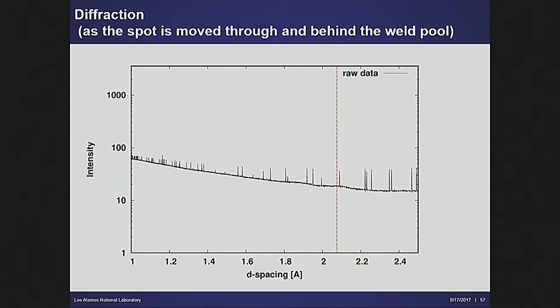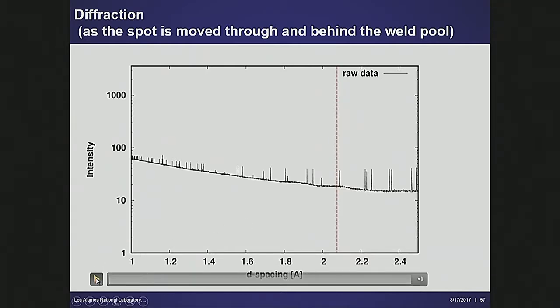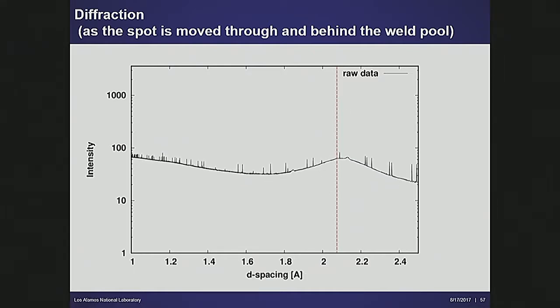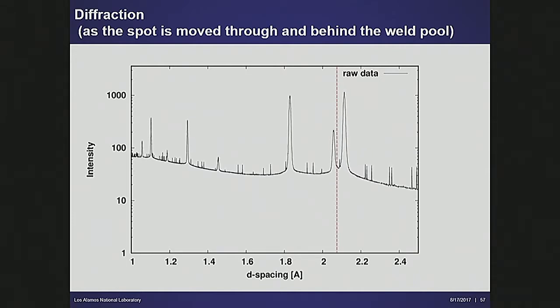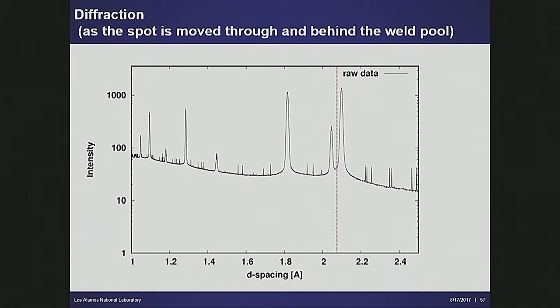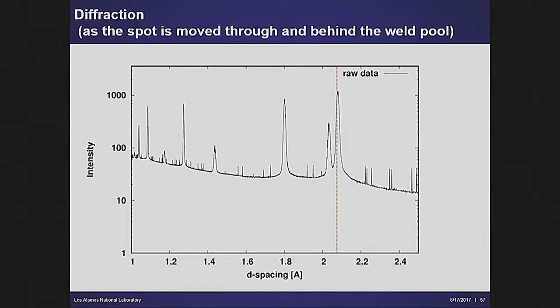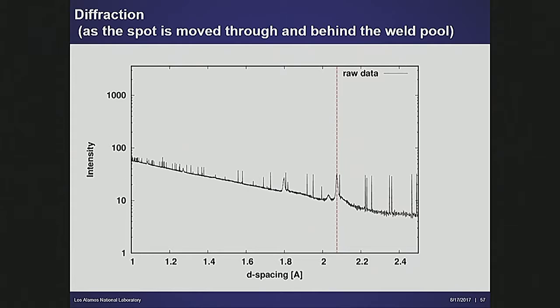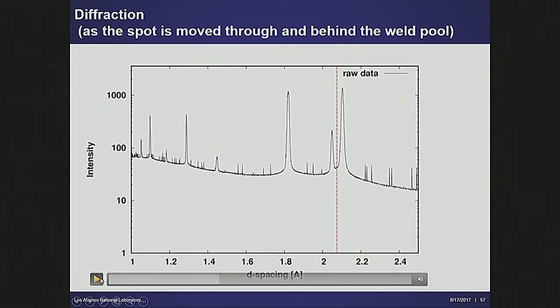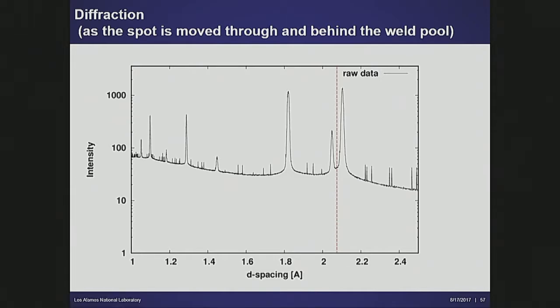If I integrate those rings to give you diffraction patterns that you're more familiar with, again, ignore the spikes. This is just the diffraction images of the integrated rings as you track it backwards and forwards. You can see the diffraction pattern changing. A couple of things to note. I'll run it again. Look for the bump here, which is molten. You can ignore that jump right at the end. When I run it again, look for the bump here.